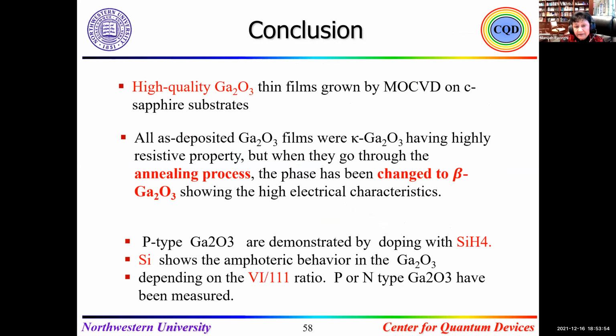By that, I would like to conclude that yes, we can have high quality gallium oxide with MOCVD on sapphire substrate, because we also did it on different substrates, including beta gallium oxide, but you don't want that, because the thermal conductivity is very low, and for the device we would like to make, we would like to have no substrate.